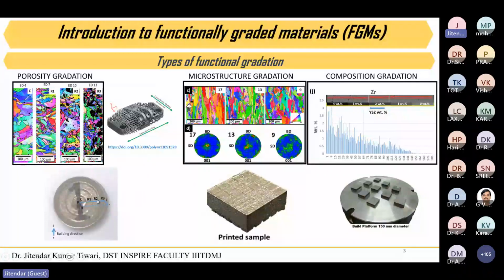Apart from achieving porosity gradation with parameter variation, designing a lattice structure or filling the bone with a lattice structure and varying the porosity can also be a very nice option for bone implant designers. In some cases we need to engineer the microstructure. This particular sample has 25 elements within it, and each element is printed at different laser process parameters. This is an LPBF process part, and that's how we can play with the microstructure.